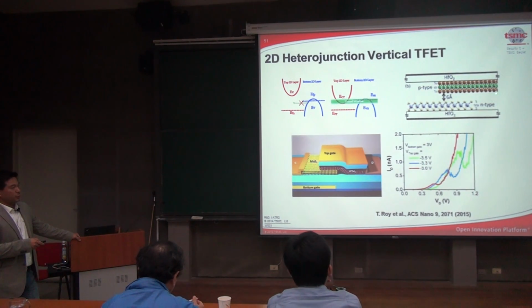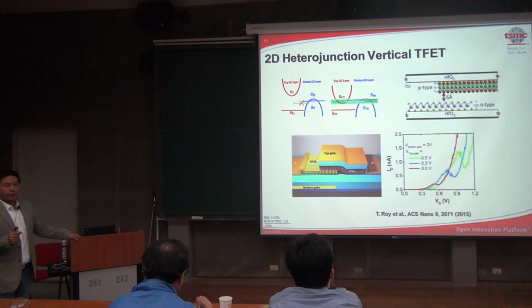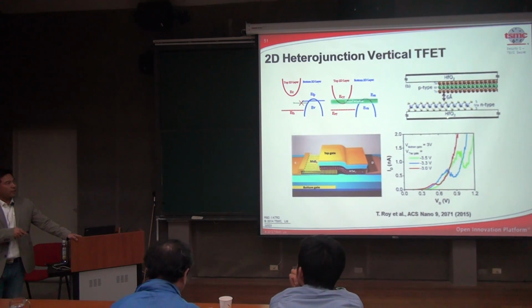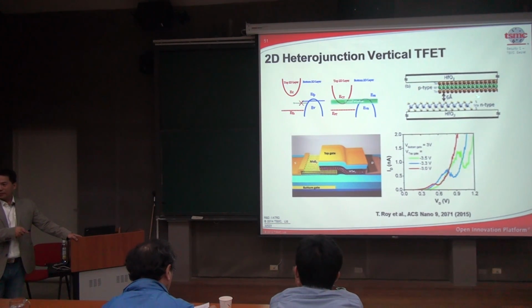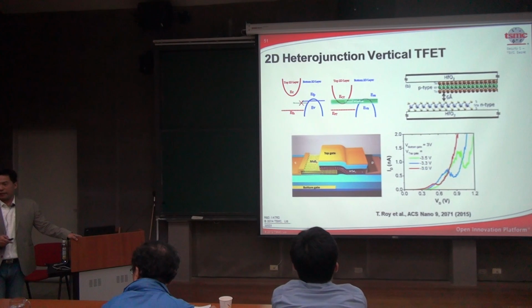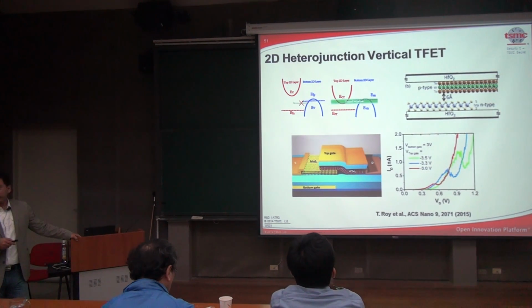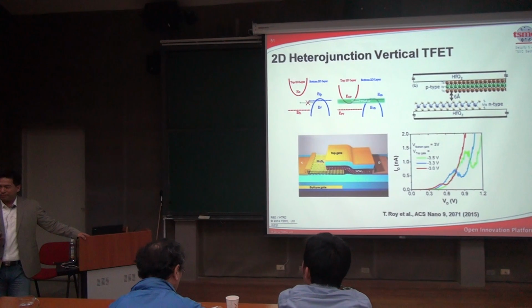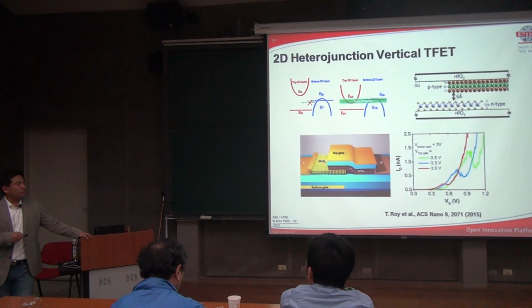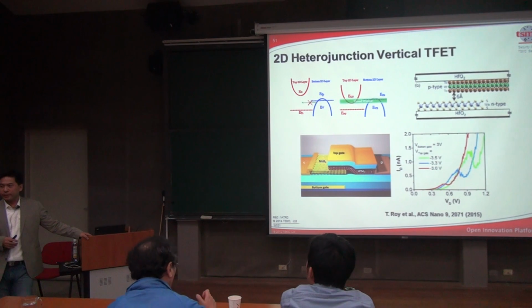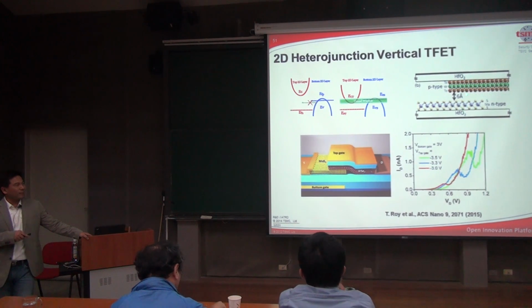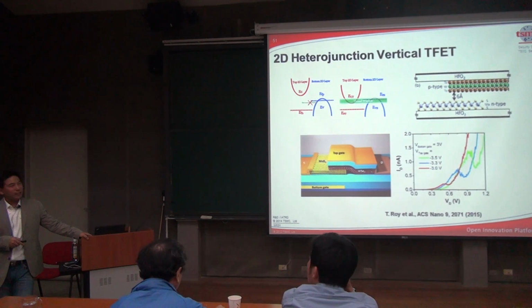So for this kind of device to work, it has certain criteria. It has to be smooth with only van der Waals interaction, and this spacing has to be engineered just right, because this is a tunneling, and we know the tunneling is very critically dependent on tunneling distance. So any variation of the tunneling here will have a big impact on your final curve. And in a planar, you mean the MOS? Yeah. They will probably take up pretty much the same footprint in the device. But how we grow this architecturally? For this case, you need a spacer. You need a spacer here, in between? Yes, just 6 angstroms actually.